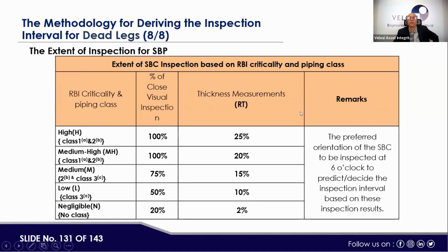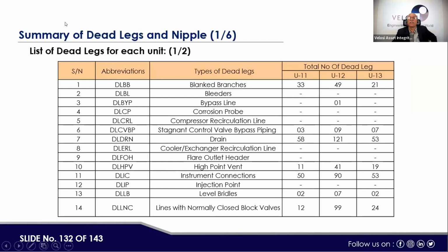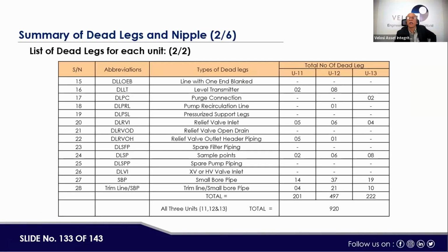Then, where we are using RT for small bore, the preferred orientation of the small bore connection to be inspected is at 6 o'clock, to predict and decide the inspection interval based on these inspection results. That was the approach we used. So here is the list of dead legs for each unit. If we see unit 11, unit 12, unit 13, it is the same aspect which I showed earlier, a more visible condition. This slide has also been presented earlier. For these other areas, we can show unit-wise the various kinds of dead legs. Total are 28 types.